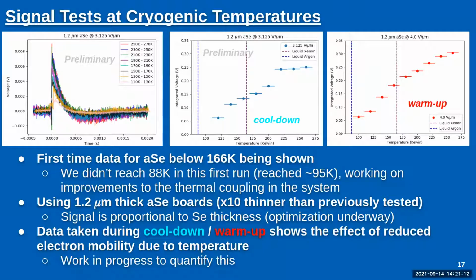We used a very thin board in this particular case, a 1.2 micrometer thick amorphous selenium board, which is 10 times thinner than the previous ones. And the signal is proportional to the amount of selenium you have. So we need to find an optimization there, but that explains why the pulses are so much smaller. The data taking during the cool down was taken at a slightly lower field than we allowed things to warm up. And you can see a reduction in what is effectively the electron mobility due to this temperature variation. And we're working now to quantify and understand the mobilities down at these temperatures in order to understand what is going to be the ultimate effect when we go down to extremely low photon sources.